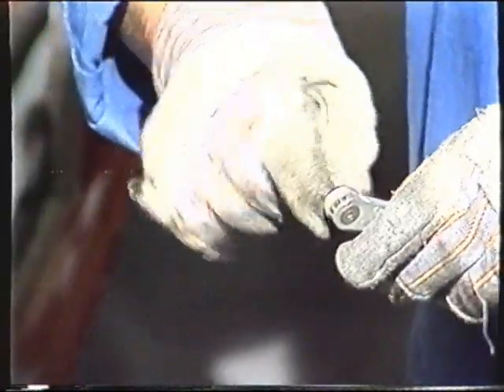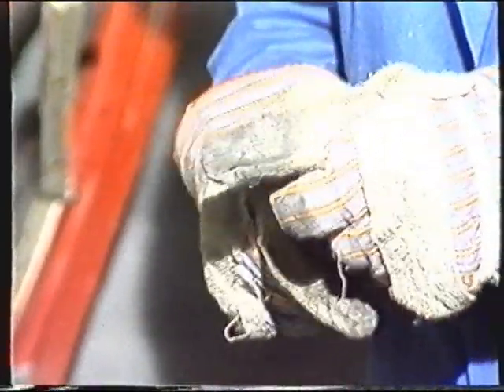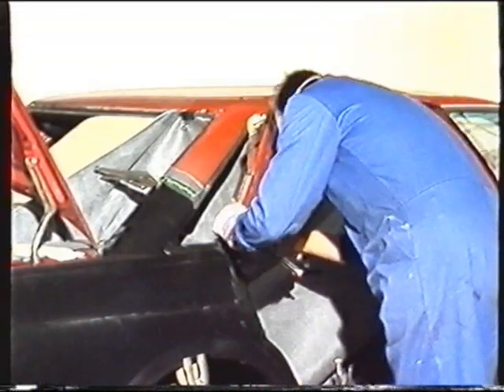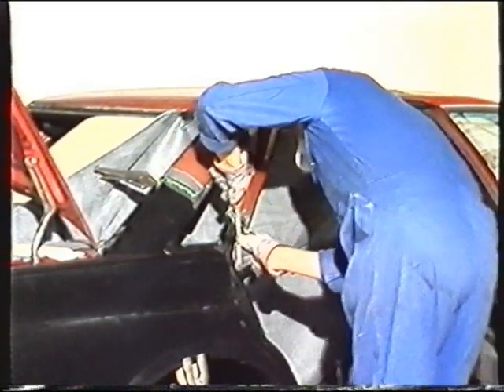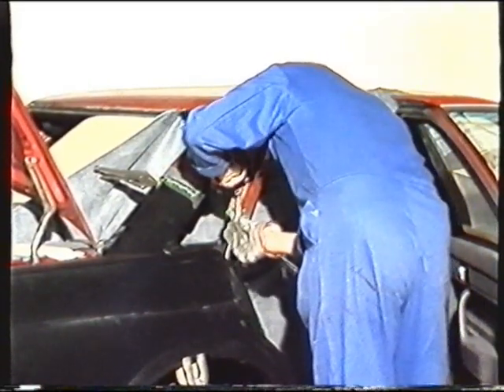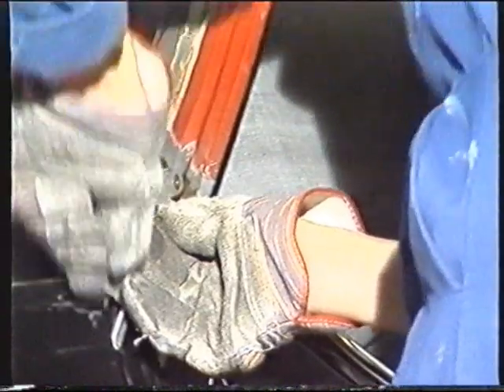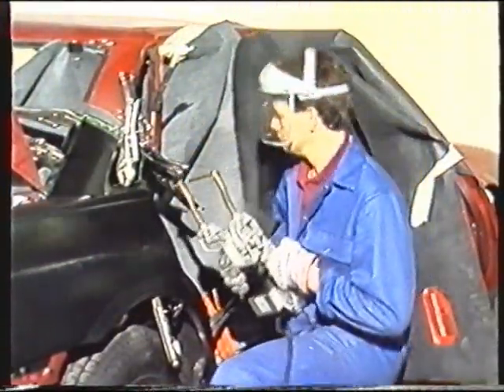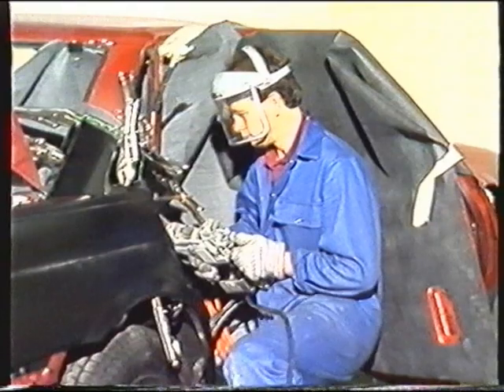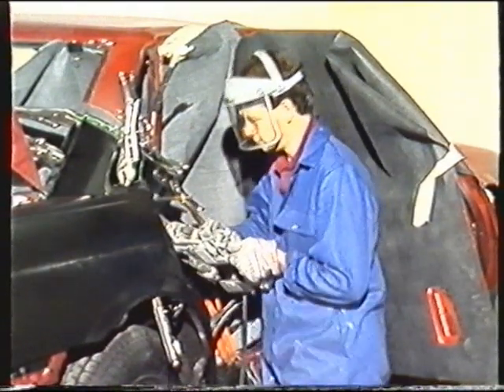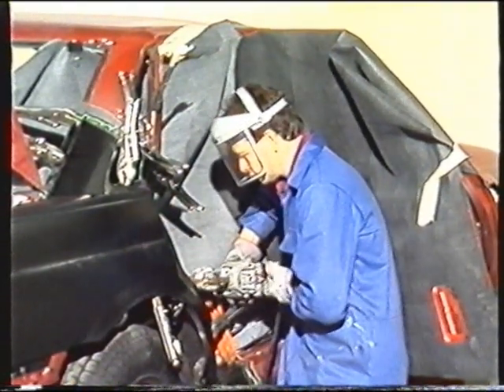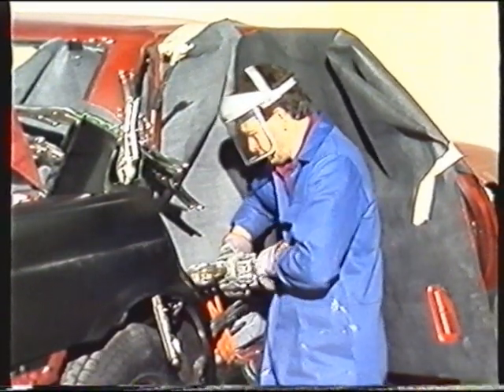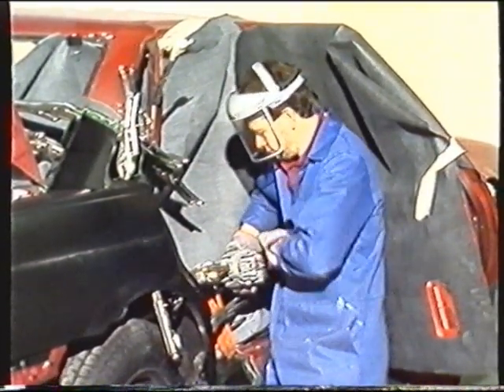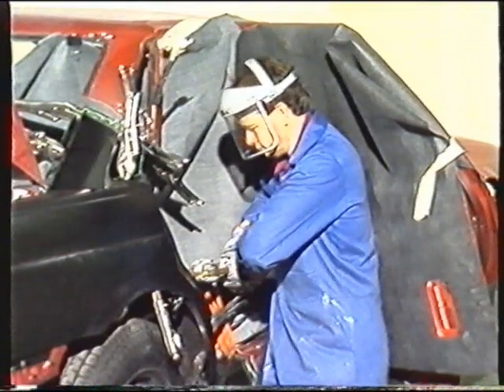The rivets are prepared and fitted through the pre-drilled holes in the panel and into the backing plates behind the 3 box section joints. Thatcham has found threaded aircraft-style rivets give better control over joint tension than conventional pop rivets. Spot welds are used at intervals of approximately 100 millimeters, but especially in critical stress areas. No weld-through primer is required here, as the adhesive fulfills the same purpose, preventing corrosion.